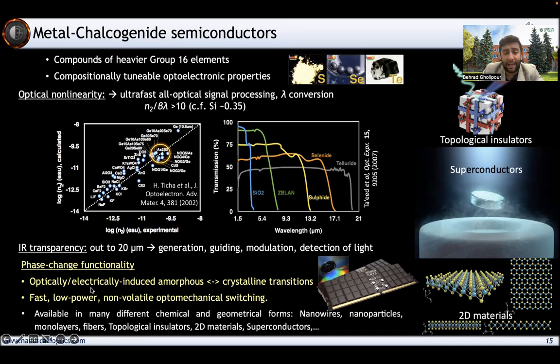And most importantly, as I said, they can be optically or electrically switched between two different states, an amorphous and a crystalline state, and this is a non-volatile transition. So you don't need to keep powering it once you've made the transition. You switch the device from one state to the next, it stays there until you come and switch it back. So this is a fast, low power, non-volatile switching mechanism, and it also has an optomechanical component to it as well, if you wish to exploit that.